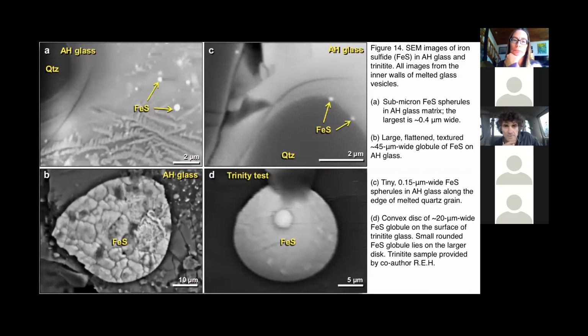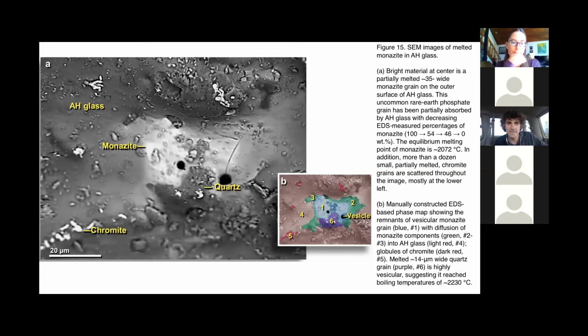I also want to look at this troilite, because we have a glass from the Trinity test. The Trinity test was a nuclear explosion in air, which created pools of glass underneath it. That test on Earth also produced troilite grains, the same as we can find in this Abu Hureyra glass. And this is a monazite. Monazite is again a grain that appeared in this picture. It was molten in a glass. So there is a lot of evidence of melting.